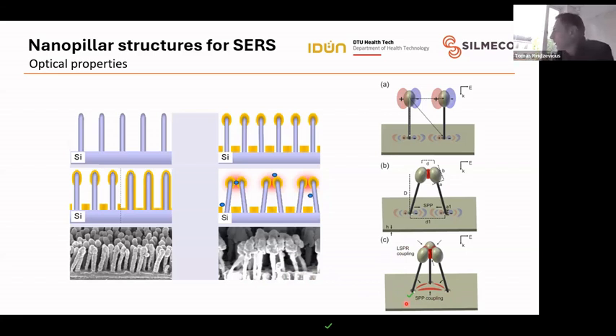So we actually managed to rip off the pillars and just test the SERS performance of the nanohole structure, and we could not see any enhancement. So even though you might potentially create some sort of polaritons here on the surface, they do not contribute significantly to the SERS signal. So we mostly think that it is because of the leaning and because of the hotspot between the pillars.